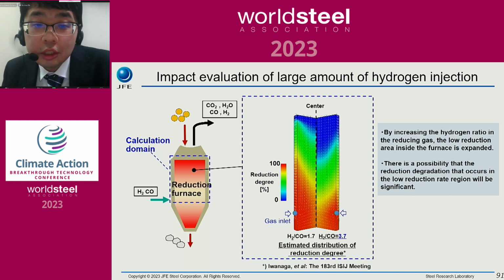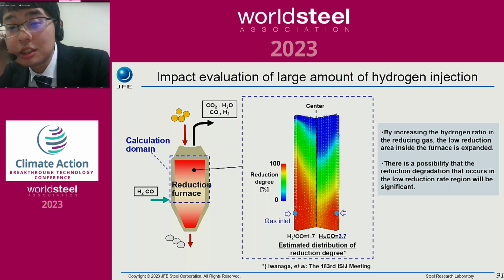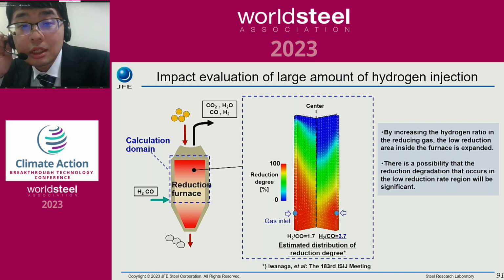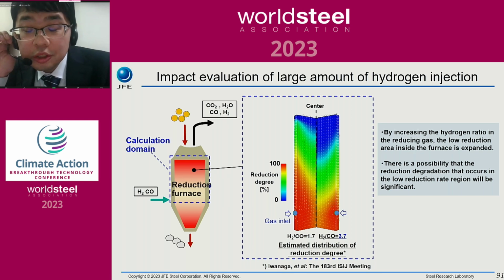Because reduction degradation occurs in the lower reduction region, it is assumed that reduction degradation is likely to occur when the hydrogen concentration increases. For these reasons, we thought that endothermic reactions should be avoided as much as possible. Please next.